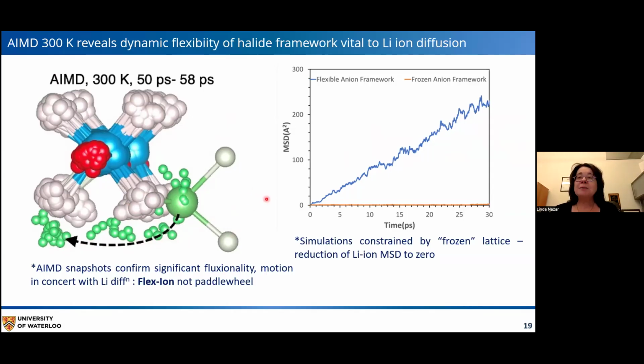And you can see this by a thermodynamically incorrect, but nonetheless useful situation where we freeze the lattice. And this is shown in orange. So in other words, there's no fluxionality allowed, versus freeing the lattice where you can see the MSD, the mean square displacement of the lithium, is now really quite significant over this time frame.